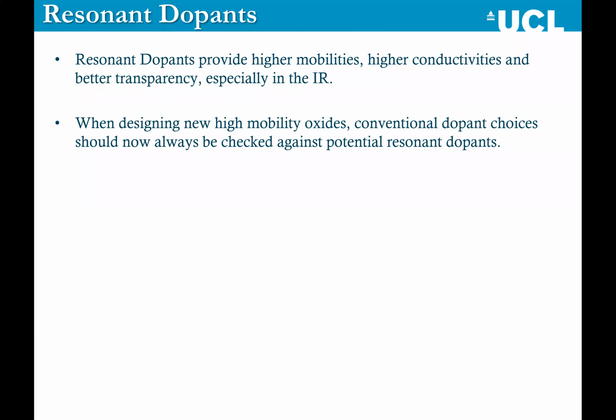So to conclude, I hope I've shown you that resonant dopants provide higher mobilities, higher conductivities, and better transparency, especially in the IR, and that for any study going forward, if you're trying to design high mobility systems, especially in oxides, conventional doping choices can be wise, but now should always be checked against potential resonant dopants. So simply doing the standard one to the right in the periodic table will give you a result, but will it give you the best result? And we think that going forward, everyone should screen nearly every dopant just to make sure.